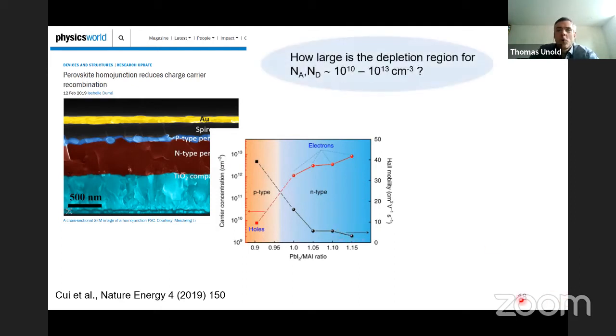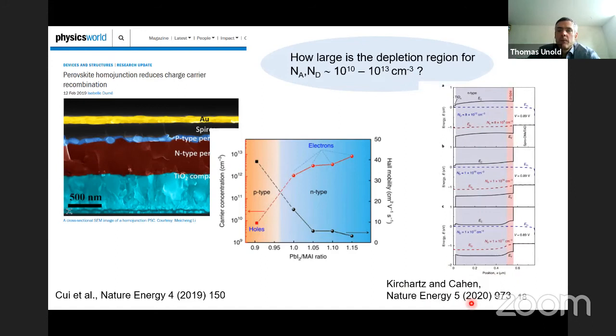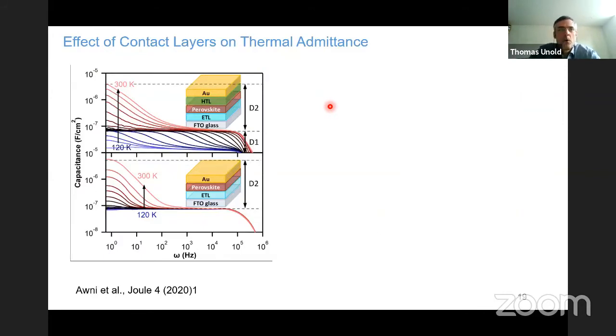And now from what I've told you already, you can think about how large the depletion region is for such low doping densities. Because if you want to have a PN junction, the depletion width has to be within the device. And you may guess already, it's way larger than this 500 nanometers. It's 5 microns or something like that. And there was very recently a comment by Thomas Kirchartz and David Cahen, also in Nature Energy, where they show that for these carrier densities that they report, there's no way there could be a PN junction in the device. So this is also what I would call a consistency check. If charge densities are reported or interpreted as PN junctions and so on, check whether this actually complies with the electrostatics.